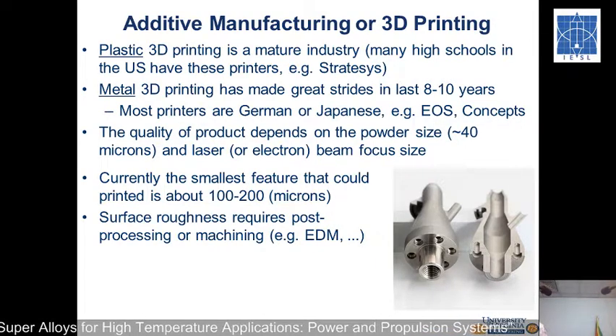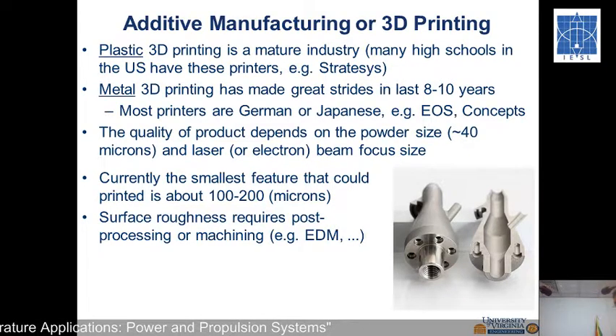So anyway, this technology is there, and another thing to notice is that the surface is rough. The roughness is essentially this 40 micron kind of surface. If you need, in fact we have another part I printed, which we have machined using EDM, electrical discharge machining, and with that, like here, you can get smooth surfaces. So you can post-process these things and get smooth surfaces as needed. Okay. So the type of architecture that you can design and build with these real metals is humongous.